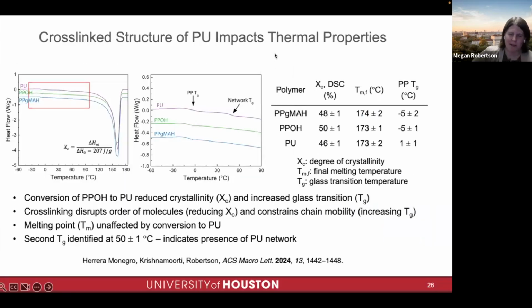Of course, this also has implications for things like the melting point, which is again unchanged. We can look at the glass transition of the polypropylene segments. There's a little bit of an increase there when we bring this polymer into the network, and the same trend with the crystallinity that I talked about with the X-rays. There is a second glass transition in the polyurethane. We attribute that to the presence of that network, in addition to the glass transition that's attributed to the polypropylene segments alone.